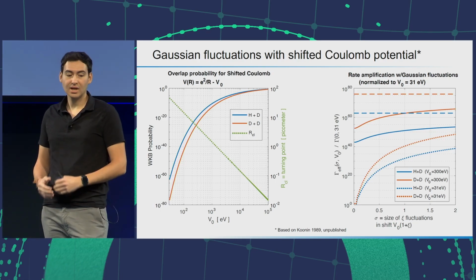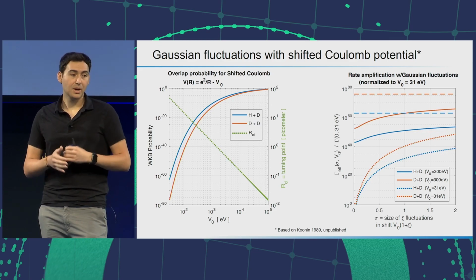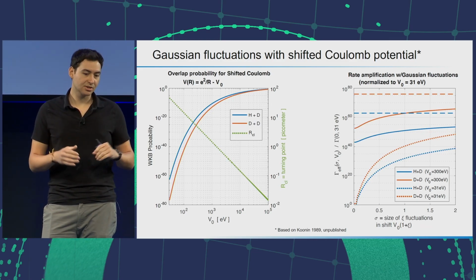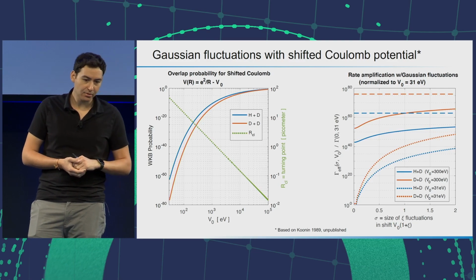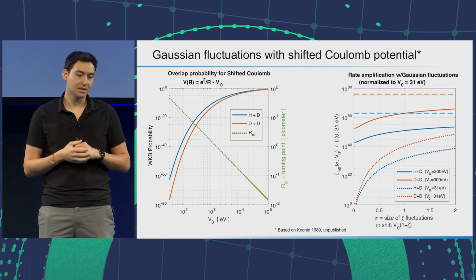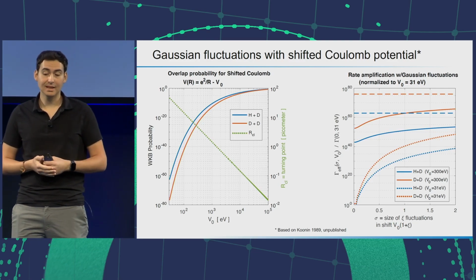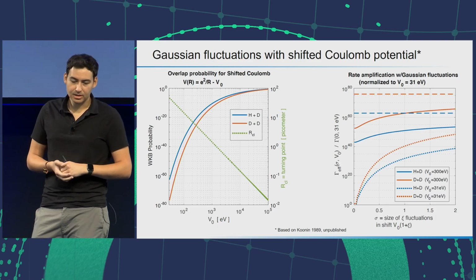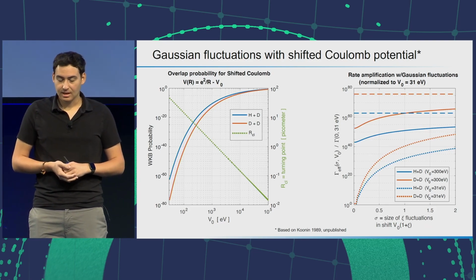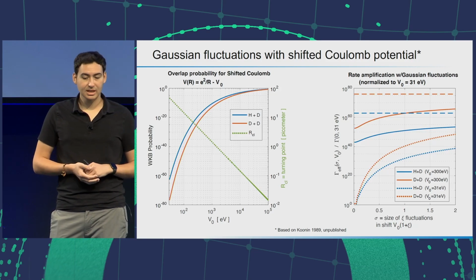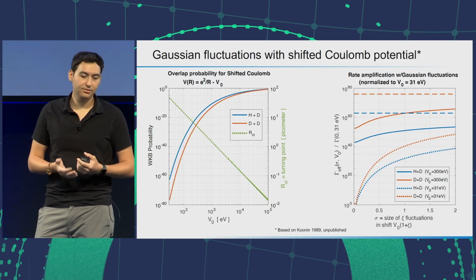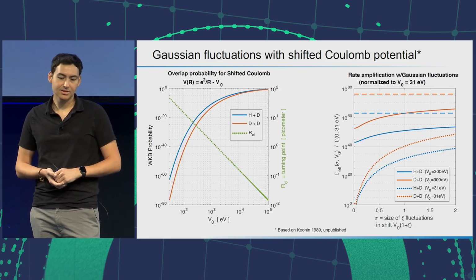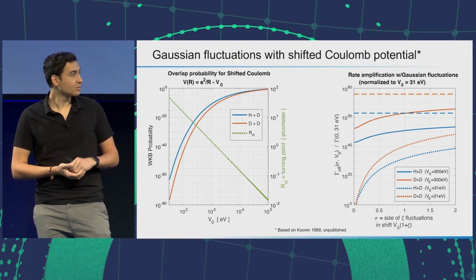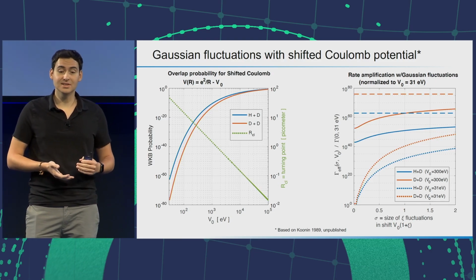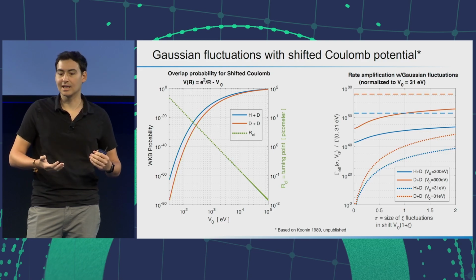So this is reaction rate enhancement above the bare case without fluctuations. And you can see it goes over a wide range. These dashed lines on top represent the theoretical upper limit, so that would be like a transparent barrier. And then the dotted lines represent taking a base screening energy of 31 electron volts, so roughly for a hydrogen molecule. The solid lines are taking a higher energy one, which we saw in the previous slides may not be unreasonable for palladium systems, 300 electron volts.